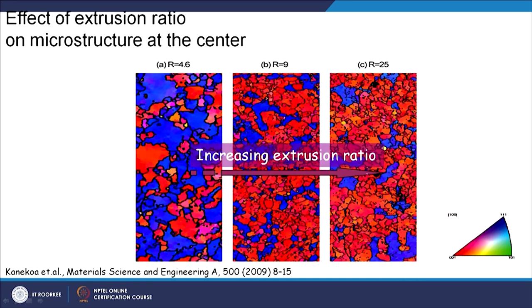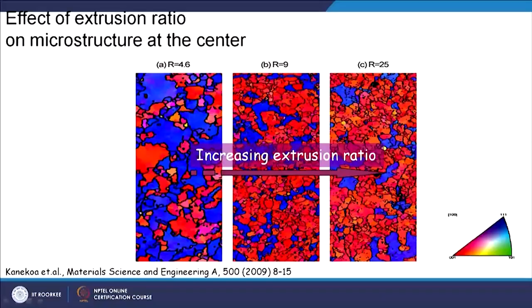This is the effect of increasing the extrusion ratio. That is the ratio between what is coming out after extrusion and what you are putting in. And as you can see, as the extrusion ratio is increasing, because you are putting more strain, the grains are very coarse here, big grains are seen. Again only two types of grains, one is red, that means the 001 axis is coming out, or blue, that means the 111 axis is coming out.